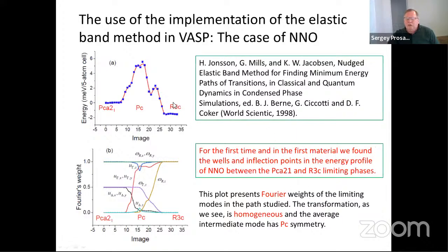We also did a calculation within VASP, with the elastic band method implemented in VASP. And we also found in the path between these two phases some wells or inflection points, which show that even first principles show the presence of the intermediate hidden states, which are not seen in experiments with bias field. And at the bottom you see the plot of how the structural modes and polar modes change during this path. So we see that intermediate states have intermediate values of these parameters.